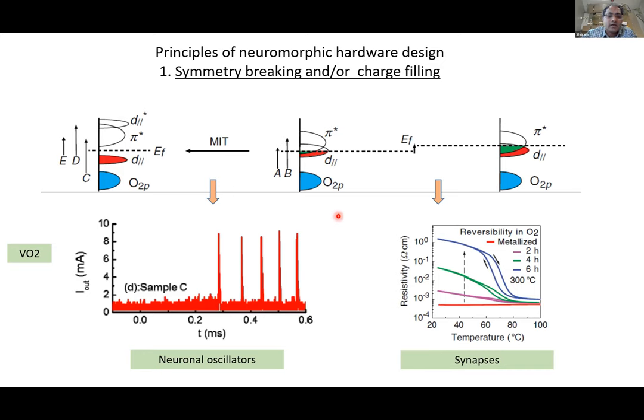One of the early demonstrations is artificial neurons. This can be done by coupling VO2 with a capacitor. As the material goes through an electrically driven phase transition, the conductance of the device changes. Whenever it goes through a metallic state, you can have current spikes, and the material can be cooled down as the voltage stimulus, for example, is removed. The dynamics of cooling allows you to build in a refractory period. So there is this periodic spiking that very beautifully emulates neuronal firing in the brain.